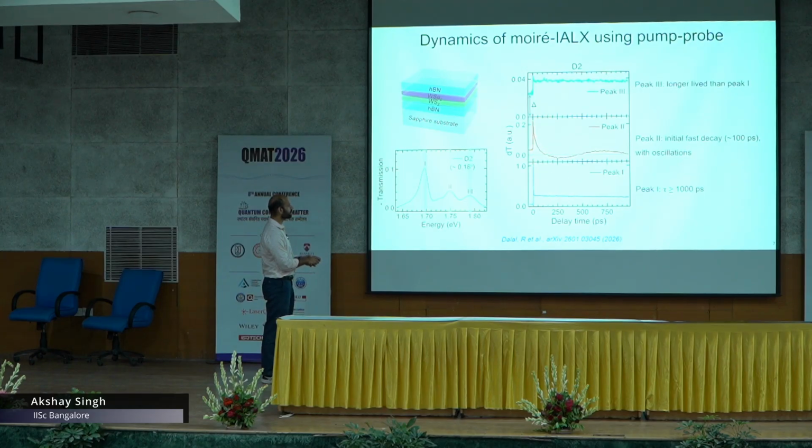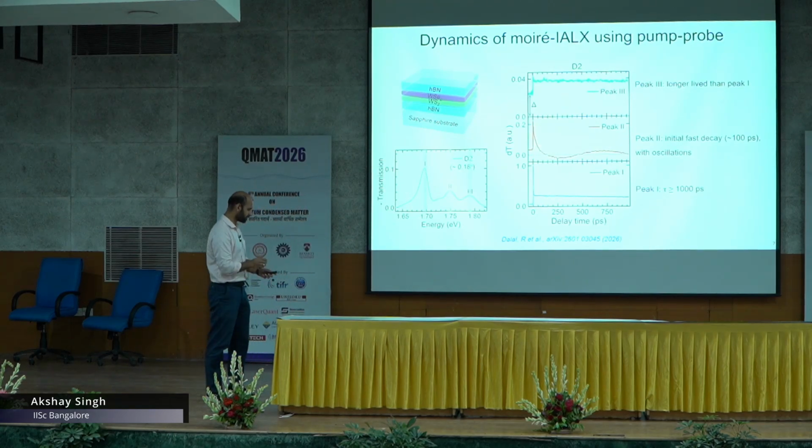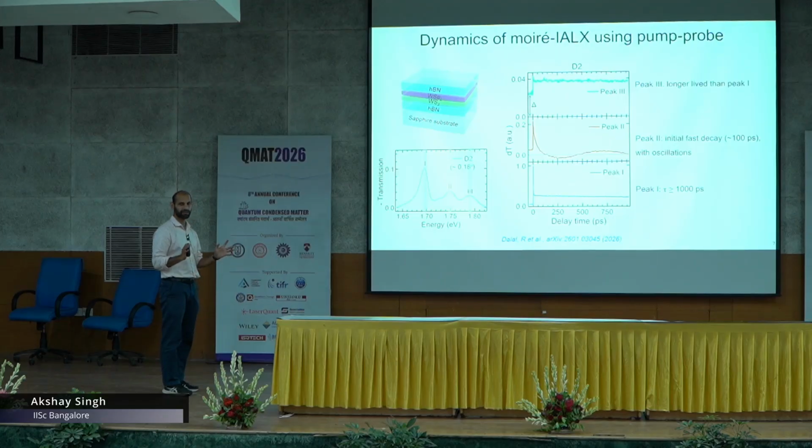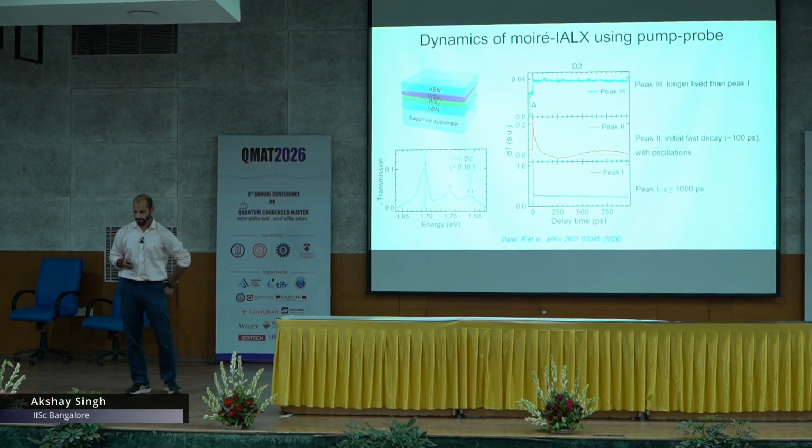The second remarkable thing about this measurement was this sort of oscillation. As a spectroscopist, whenever I see a new peak or some oscillations, that at least gets me excited to understand what's the underlying physics here. But the remarkable part is that these oscillations are, at least in terms of ultrafast science, extremely slow. These oscillations are of the order of about 300 to 500 picoseconds. We'll get back to these oscillations in a bit.